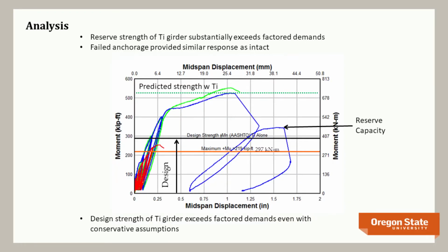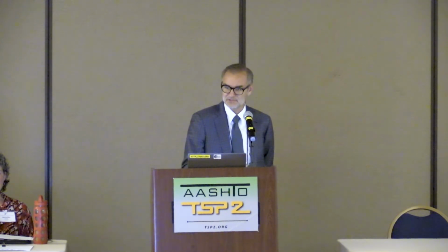The red is the control. Remember, I had one that I failed first and then repaired? That's the green one. That's the highest strength. The blue one is the one that I didn't fail first, and then I applied the titanium, and it actually gets lower strength. And you might say, wow, so if you fail it first and add the titanium, you get the best performance. And the answer is yes. And the reason for that is the titanium is what controls the strength.